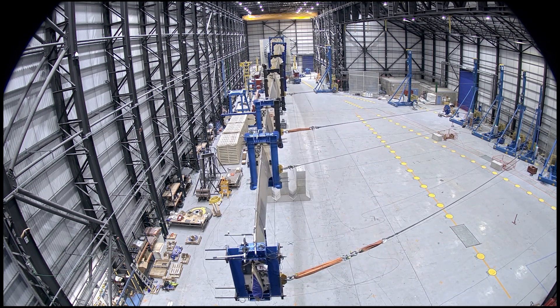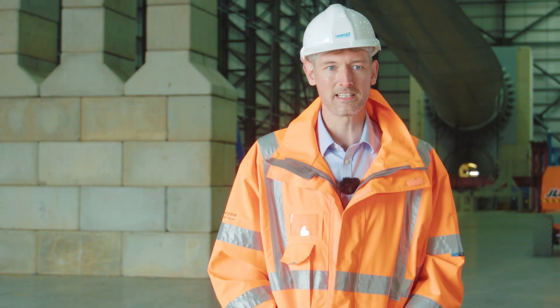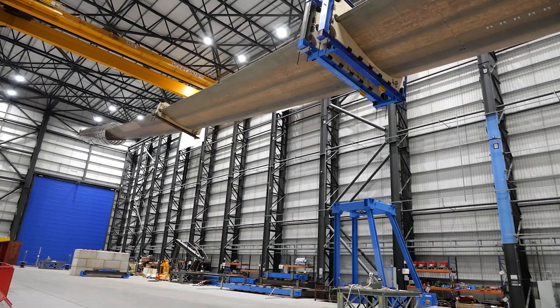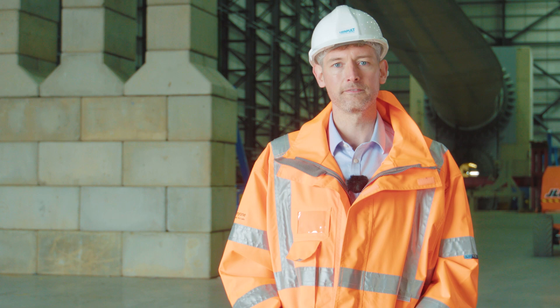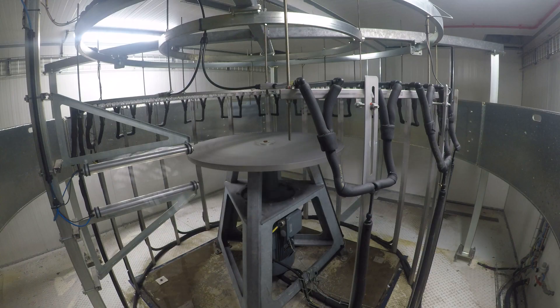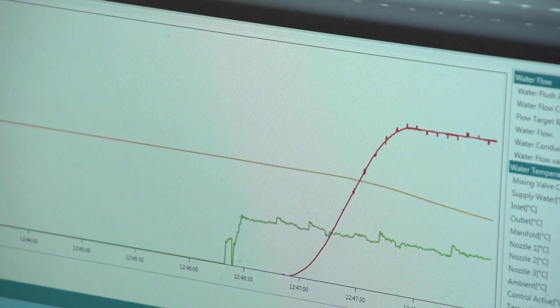It's a huge amount of force we're putting through the blade. The other type of test we do here is a fatigue test which is aiming to replicate the 25 year design life of the turbine, where we just bend the blade back and forth for perhaps two or three million cycles. That whole test process for a structural test for a blade can take nearly a year for a blade of this size. The other type of testing that we do here for blades is rain erosion testing — we can do very finely calibrated rain erosion trials of different types of protection.